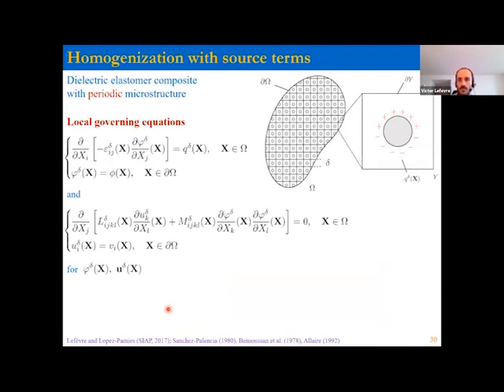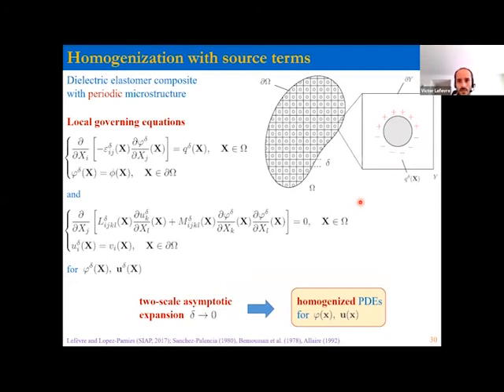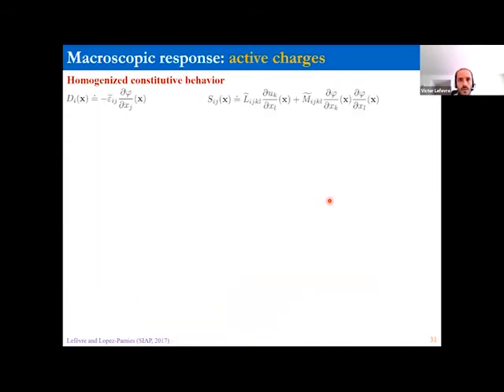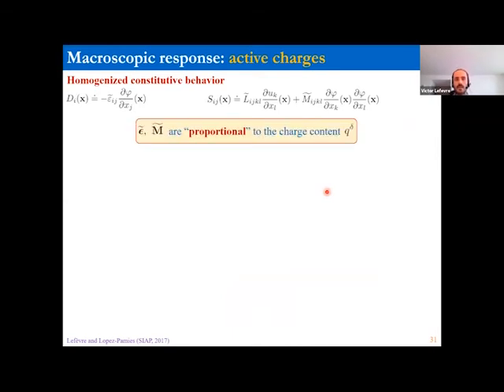So we did some analytical work to look at this. I'm not going to go into the details, but now we have a composite as well as a distribution of space charges. I'm going to skip all the details, but we're able to come up with governing equations for the macroscopic response of these composites, now with space charges, in the small deformation limit. What turns out is that these composites behave as regular elastic dielectrics. But now there's an important catch. The catch is that their permittivity, epsilon tilde, and electrostrictive coefficients, these are the two quantities that we're really interested in.